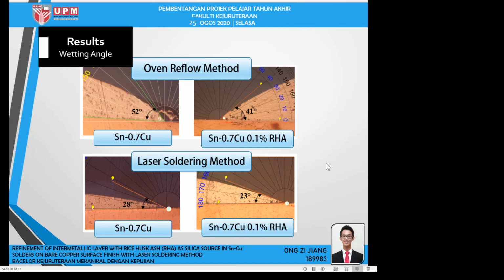So this is the wetting angle analysis. We can clearly see from the results obtained that the wetting angle for oven reflow is higher than for the laser soldering method. For the oven reflow method, the plain tin 0.7% copper solder has a 52 degree wetting angle, compared to the addition of 0.1% RHA which has a 41 degree wetting angle, which means there is about a 20% decrease after the addition of the RHA. For the laser soldering method, it is 28 degrees for the plain solder and 23 degrees after the addition of the RHA.